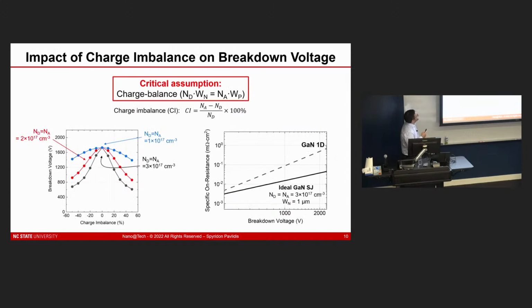And then the other really critical thing that you have to think about when you're designing and making a superjunction is charge balance, or the other way around, be worried about not having charge imbalance. Because the math on how these devices work assumes that your charge is balanced between your lateral P and N junction regions. And you can see the consequence of not having that in this chart here. If you start to deviate from a charge balance scenario, you see a roll-off in your breakdown voltage.